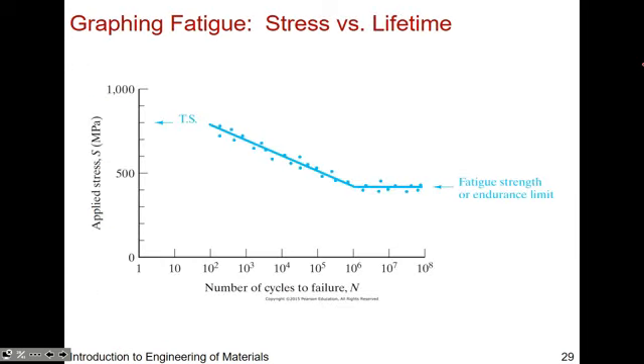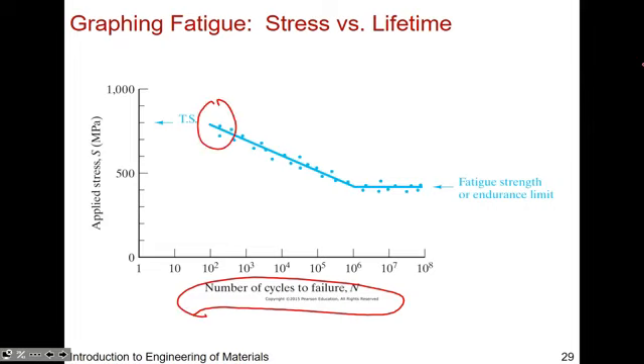If you plot the applied stress, S, and then the number of cycles to failure, you could see that if you apply very high stress, very close to your tensile strength, you're not going to last very long. Here it's 100 cycles. However it's being used in service, it's not going to last very long. If you want it to last much longer, you can reduce the applied stress, and under cyclic loading you could see here, 10 to the 5th, 10 to the 6th.